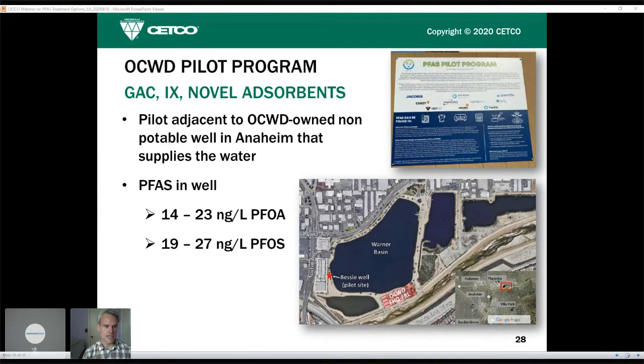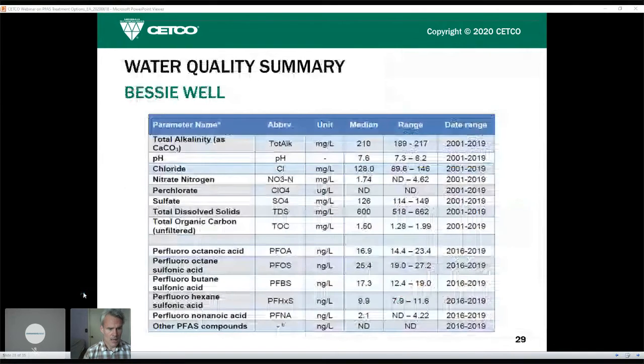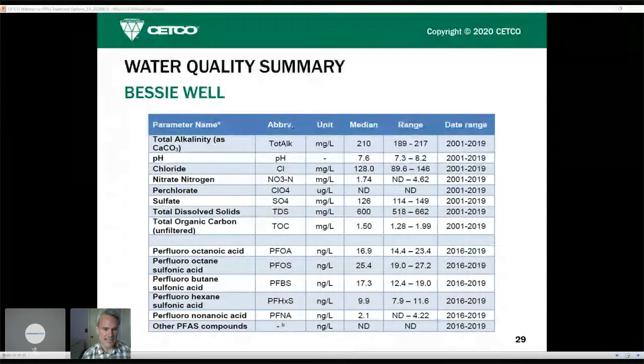So just to note, if you look at the groundwater levels of PFOA and PFOS, they are pretty low. So we're talking in the 15 to 30 nanogram per liter range. So we were shipped water from Orange County, and you can go to the next slide, to the lab where we could do some rapid small scale column tests. And I'll talk about some results in a minute, but this is a table just showing general water quality as well as PFAS levels for this groundwater. So again, we have groundwater, relatively low TDS, about 600 milligrams per liter. TOC is fairly low, about 1.5 milligrams per liter. And then you can see the levels of perfluoroalkyl acids, some shown, are generally quite low. You can go to the next slide.